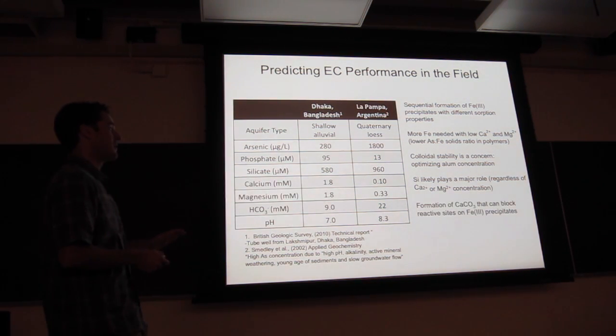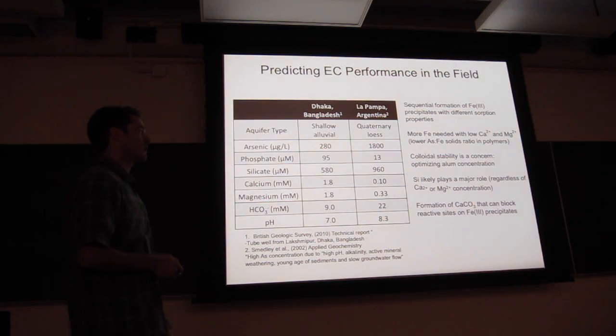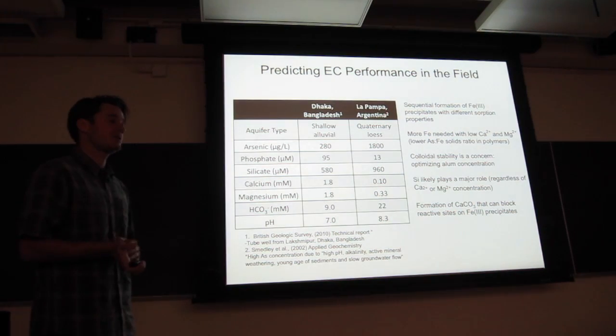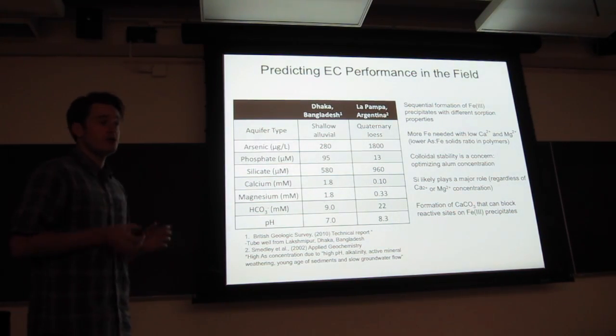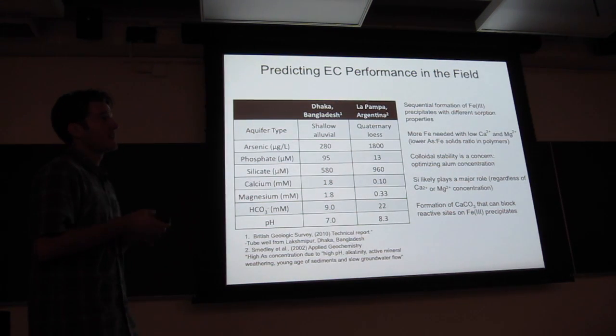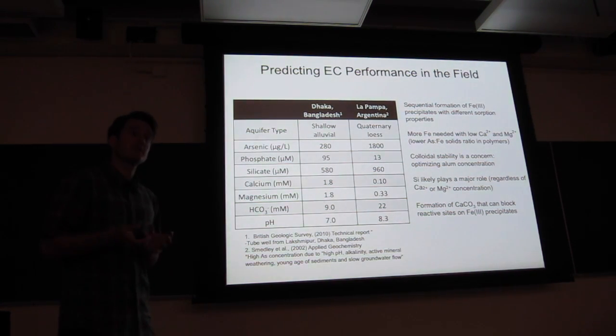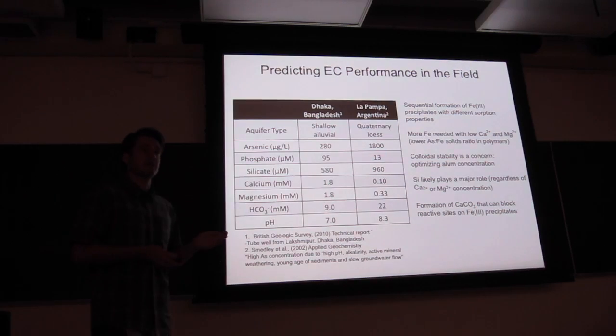One more caveat is that in groundwaters that are near supersaturation with respect to calcium carbonate, you might have calcite forming that strongly associates with the iron oxide, and that can block surface sites on the precipitate.